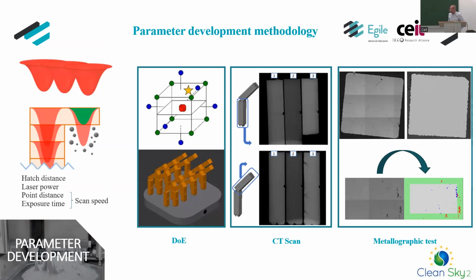As you can see, some test tubes were manufactured, some vertical and diagonally. After this, we CT scanned them in order to check for cracks and micro cracks. And after that, we did a metallographic test in order to check the microstructure and possibilities of porous sections. Once we've done all this, with image treatment we are able to quantify the density and the porosity of these test tubes.